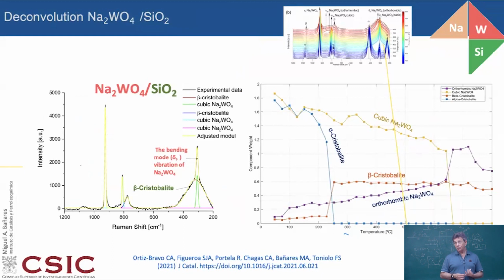Well, in the absence of sodium, basically you are dealing with the bulk tungsten oxide, and that system is not performing well. You need the presence of sodium, and you need the presence of manganese, and the manganese also has an importance regarding the oxidation state in addition to the structural things. So basically what we're observing here is how different phases evolve with temperature at different heating temperatures. And then you can see structural changes and how these correlate with the performance of this material for the conversion of C1 molecules. Questions, concerns, modulation, Raman,